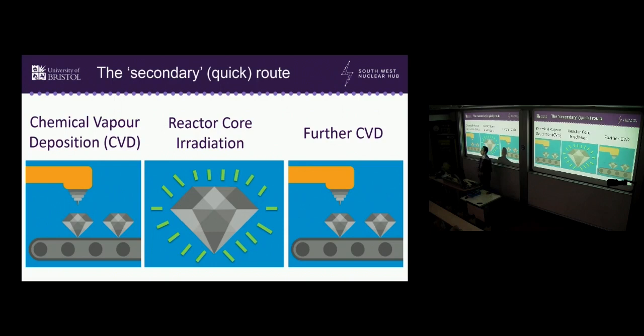I can grow a carbon-13 diamond, and I can grow that in a deuterium plasma, so that I've got a diamond which contains deuterium and carbon-13. I can then take that diamond and put it in a nuclear reactor core. Essentially a bit like putting it in an oven, I leave it there to bake for a bit. And after about a month, I've nicely activated that diamond. I've converted a good proportion of the carbon-13 to carbon-14 and a good proportion of the deuterium to tritium.